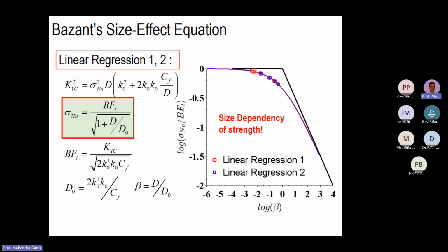Laboratory tests are usually done for small sizes, so you determine the strength there. And if you use that strength for design of a real life structure, then the actual strength of the structure is smaller compared to the laboratory test. So that will be a wrong design. You have to account for the reduction in strength, and here quasi-brittle fracture mechanics comes into the picture.